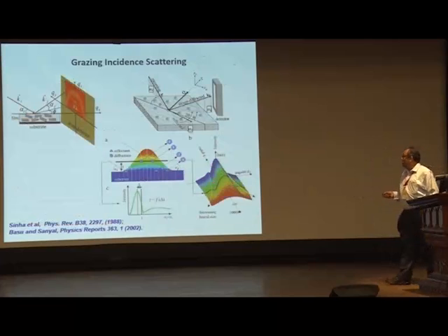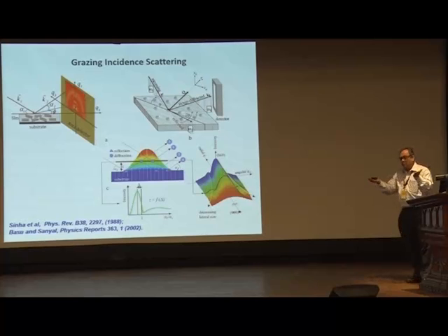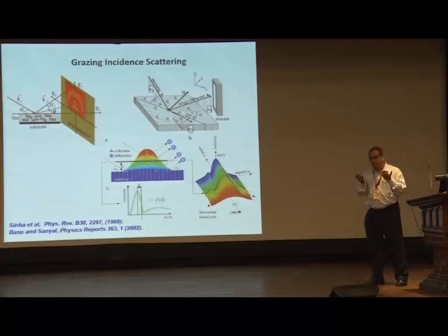One way to do that is by reducing the angle of incidence. So you have a grazing angle of incidence. I'll tell you why. As I have shown, all these dots are on top of a gallium arsenide substrate. So the idea is you must reduce the signal from gallium arsenide. It should be coming from the top surface where the dots are.